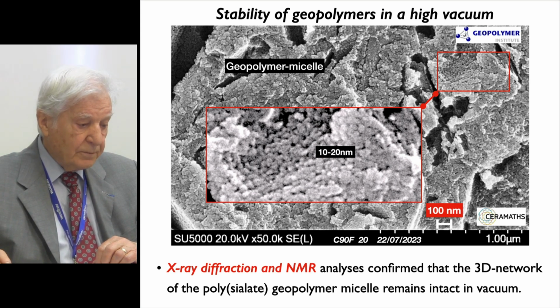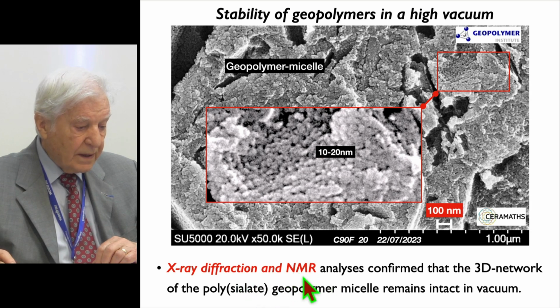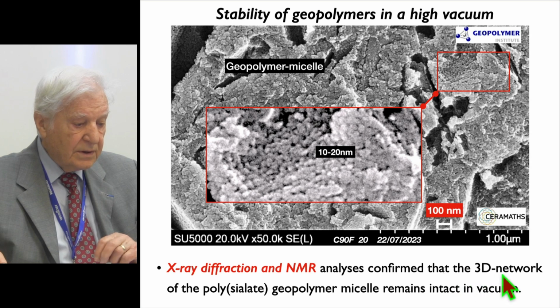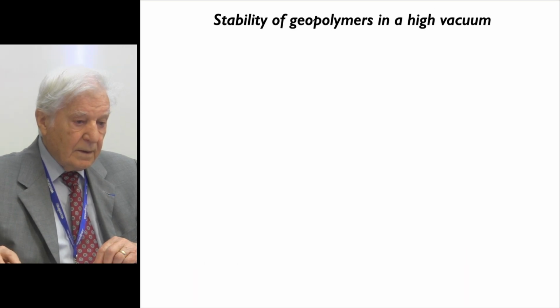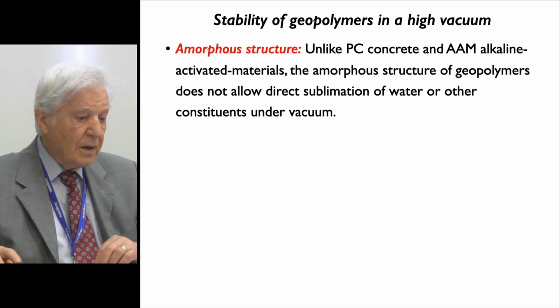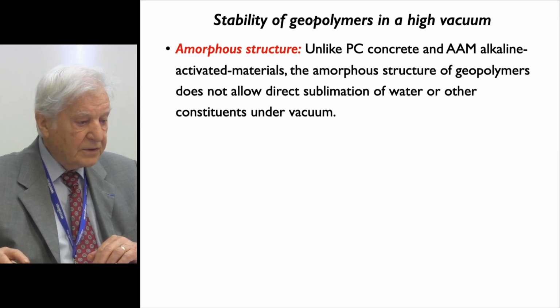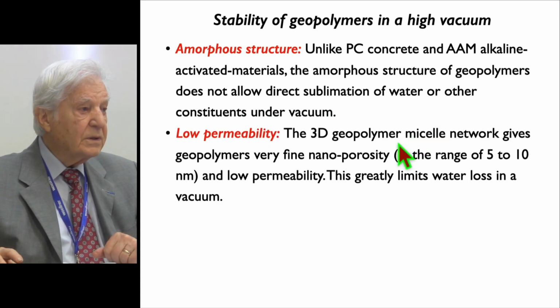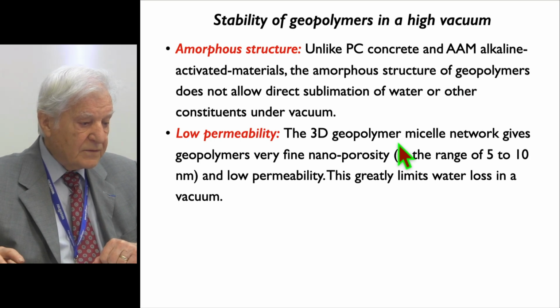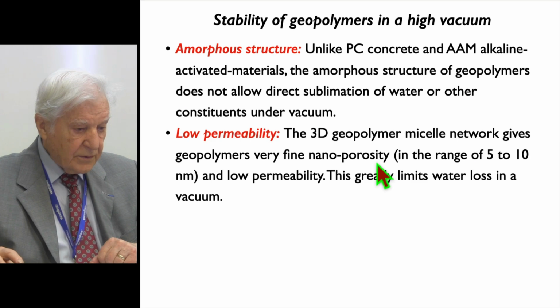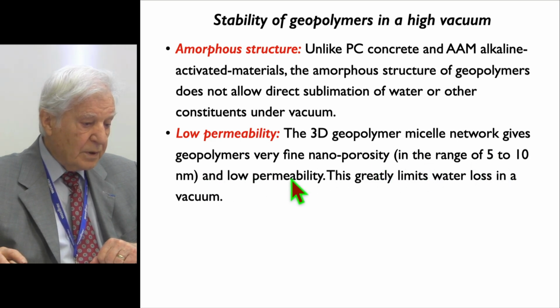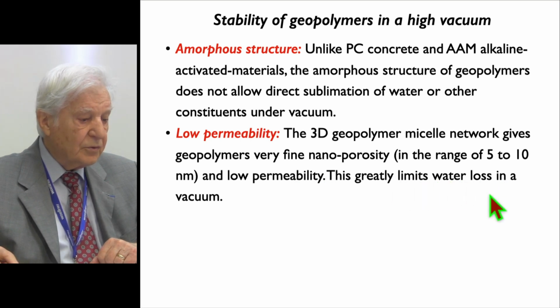Stability of geopolymer in a high vacuum. X-ray diffraction and nuclear magnetic resonance analysis confirm that the 3D network of the polysialate geopolymer micelles remains intact in vacuum. There are several reasons for the stability of geopolymer in vacuum. Amorphous structure. Unlike Portland cement and alkali-activated materials, the amorphous structure of geopolymers does not allow direct sublimation of water or other constituents in the vacuum. Low permeability. The 3D geopolymer micelle network gives geopolymers very fine nanoporosity in the range of 5 to 10 nanometers and low permeability. This greatly limits water loss in a vacuum.